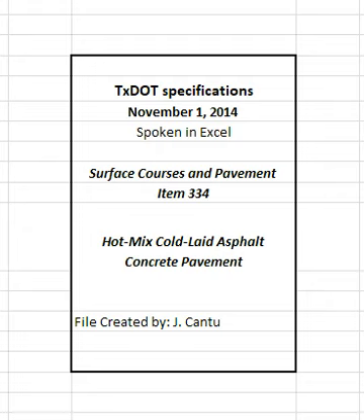4.7 Irregularities. Immediately take corrective action if surface irregularities, including segregation, rutting, raveling, flushing, fat spots, mat slippage, color, texture, roller marks, tears, gouges, streaks, or uncoated aggregate particles are detected. The engineer may suspend production or placement operations until the problem is corrected. Remove and replace any mixture that does not bond to the existing pavement or has other surface irregularities identified above at the expense of the contractor and to the satisfaction of the engineer.